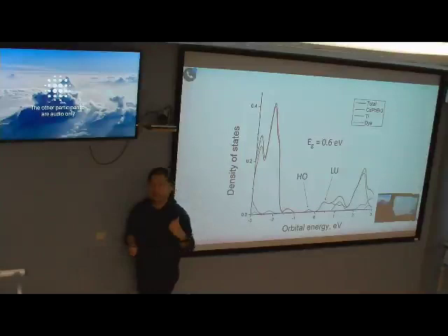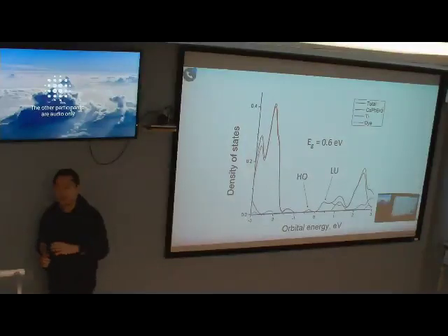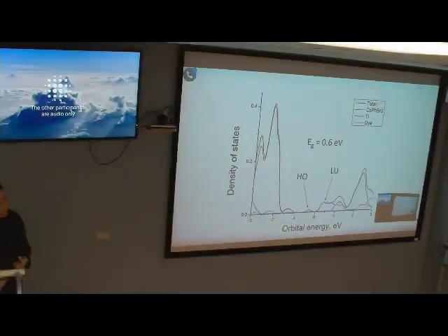This is without any external electric field. So it's clear who is organic dye and who is titanium. So if a photovoltaic cell will be done, the maximum voltage from this cell will be 0.6 volt, no more, right?